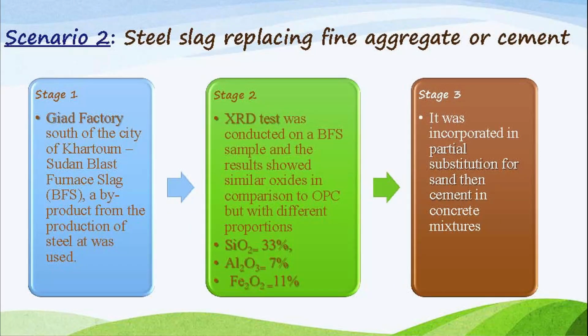Trial number 2 talks about steel slag replacing fine aggregate and cement. It has 3 stages. Stage number 1, we collect the material from Giad Factory, south of Khartoum city. Stage number 2, XRD tests were conducted on the BFS samples. Stage number 3, it was incorporated in the partial substitution for sand and then cement.